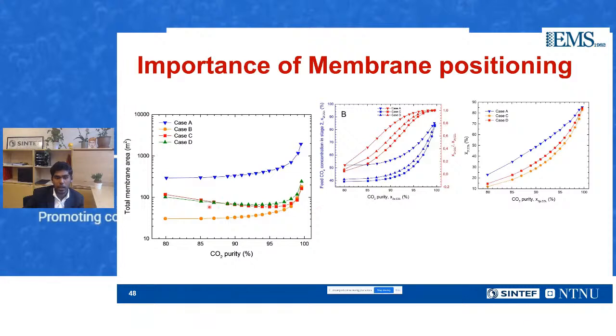So which means that something is happening in the system of cases C and D where the membranes are different in both the stages. Case A has a high selectivity membrane in both the stages, and case B has high permeance membranes in both the stages. So that's the reason why they follow a simple trend. But when you mix and match the membranes, you have trends which compensate each other. So we wanted to look into detail what actually has happened in the system. So what we did is that we checked the exit concentration going into the permeate, which is the purity of the second stage, which is basically the outlet CO2 concentration of the second stage.